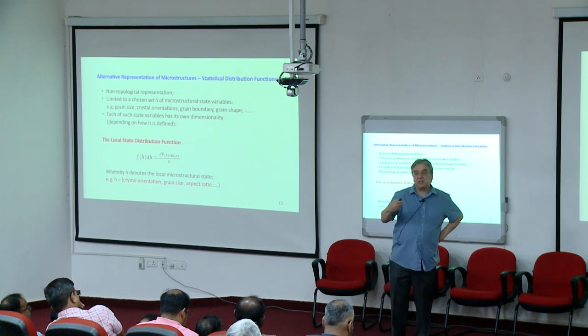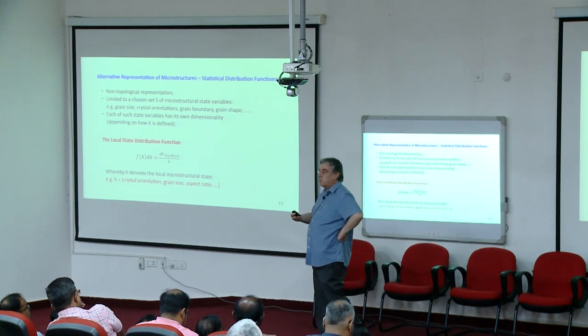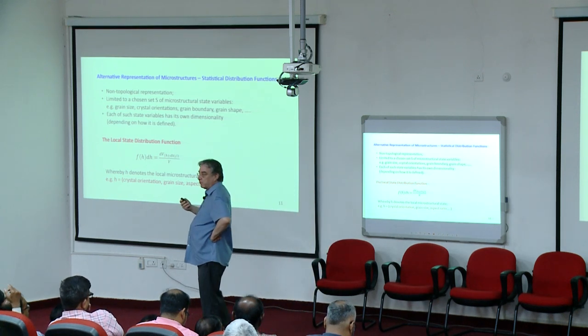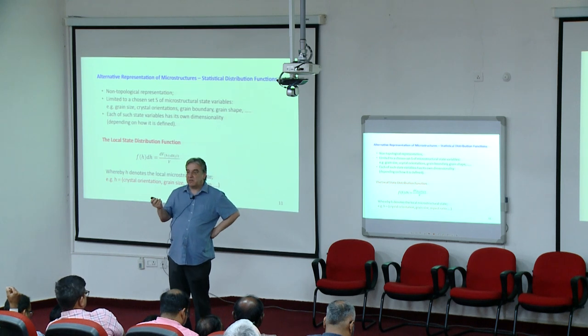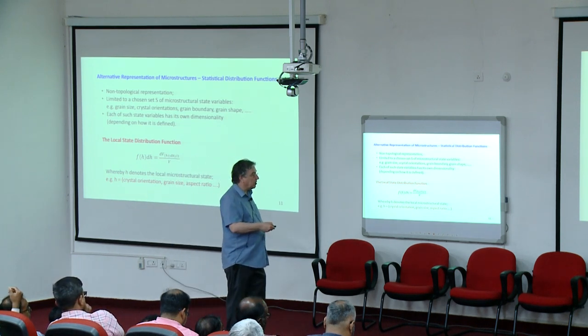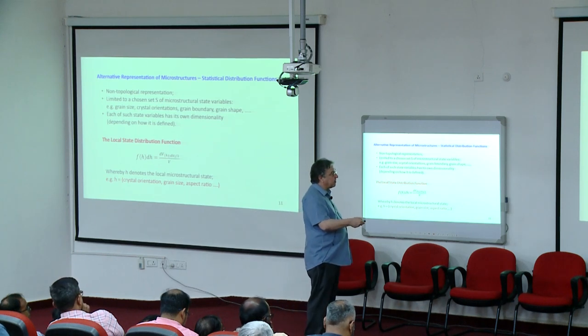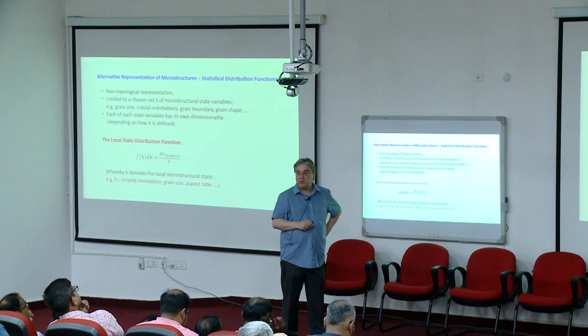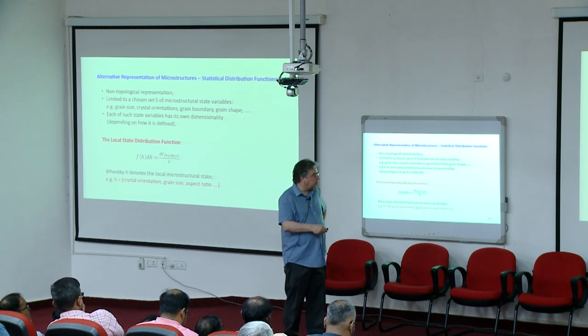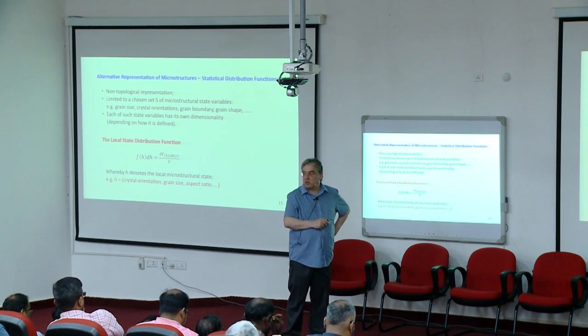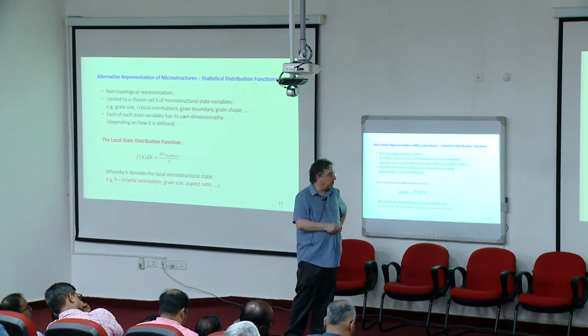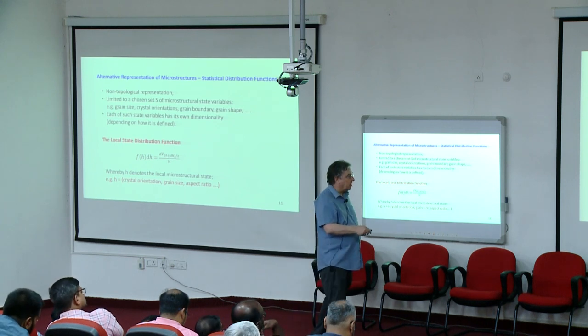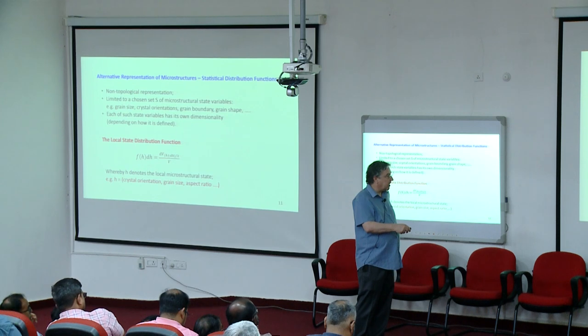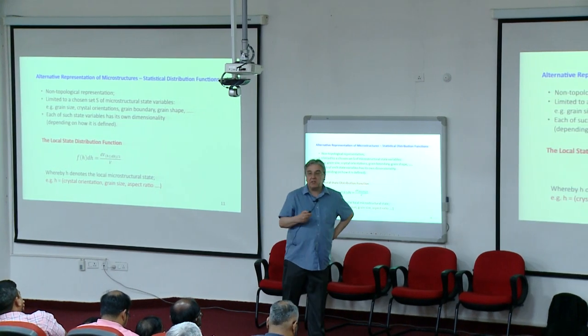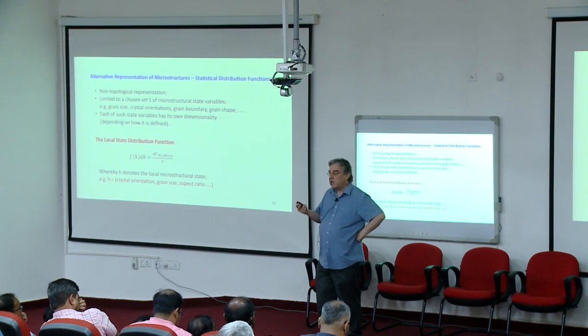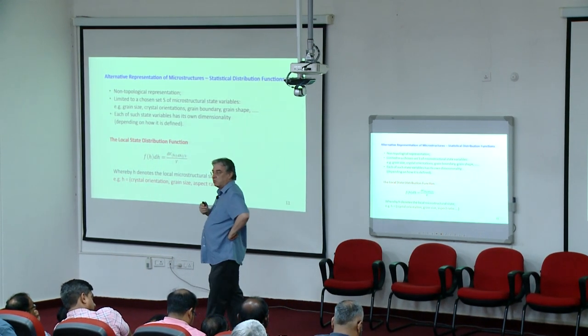This is a distribution function in the same sense that you know distribution functions of probability. But here we don't have distribution functions of probability. We have rather distribution functions of volume fraction. Because the H represents this set of state variables. If you consider n state variables, then H will be an n-dimensional vector in the n-dimensional state variable space. And here on the right-hand side, this is the volume fraction of material that has the state variable within an infinitesimally small environment around H, in the same way that you would define a probability distribution function.